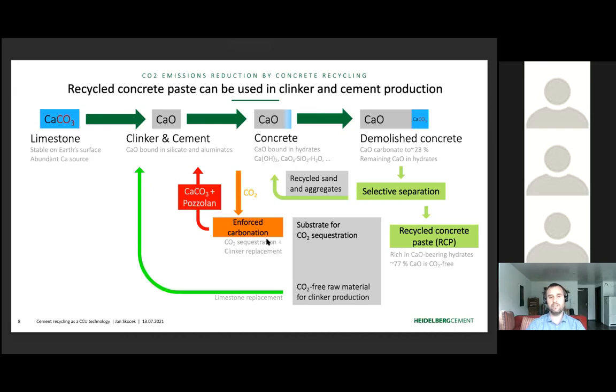But as now we are not carbonating a big piece of concrete structure, a thick wall, let's say, but a very fine powder. And we are not carbonating with the CO2 concentration as in the atmosphere, 0.04%, but some 15 to 20%, which is the CO2 concentration in the kiln gases from clinker production. This carbonation reaction happens very quickly, and with the technologically feasible time, we can fully carbonate this RCP, fully bind the original process emission from limestone decomposition.